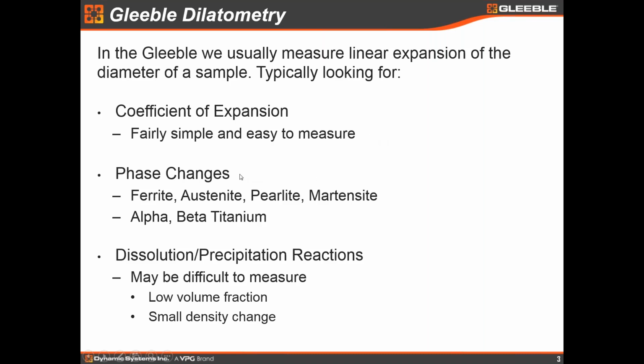The other thing, and probably the primary thing that people use Gleeble for in dilatometry mode, is to measure phase changes. Phase changes are critically important in the treatment of steel, as the steel changes crystal structure from ferrite to austenite and can absorb a lot more alloying elements in austenite. Then we typically quench back down at a fast cooling rate from that austenite in order to get several of the different structures that you can get in steel, pearlite and martensite being two of the most common ones, also of course bainite, and then the spheroidized carbide, perhaps if we cool very slowly and let the pearlite carbides spheroidize.